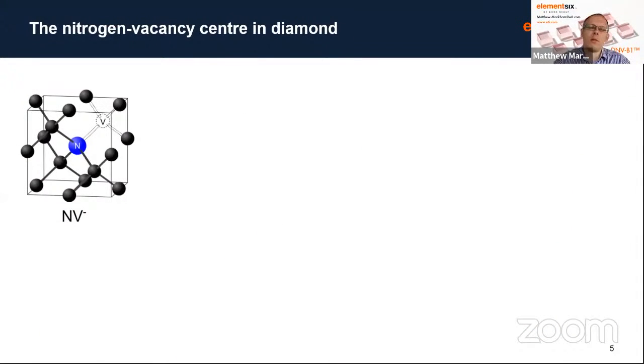Most of diamond quantum technologies is based around the nitrogen vacancy defect. There are other defects out there that people are working on for different applications. However, I think the NV is probably the main workhorse because of its very interesting properties. Specifically, the nitrogen vacancy defect in diamond consists of nitrogen replacing one of the carbon atoms, and next to that is a gap in the lattice, or vacancy. Specifically, it's the negative charge state that we use.